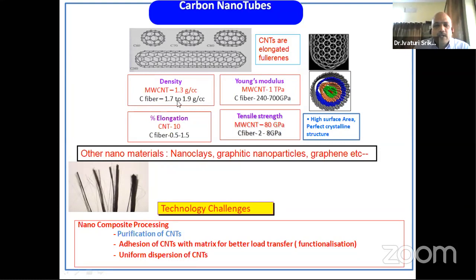Okay. Now let us see the comparison of the carbon nanotubes with carbon fibers. As I told, carbon fibers are the workhorse reinforcements today for almost all aerospace systems. Carbon fiber density versus nanotube density, you can see here, is around 30-40% less. Then the modulus of carbon fibers is around 700 GPa, varying with the type of fiber. There are different grades of fibers. Against that, carbon nanotubes have very high modulus. Then the strength of carbon nanotubes is also reported to be very high: 2 to 8 GPa for carbon fiber, against almost 80 GPa reported for nanotubes.